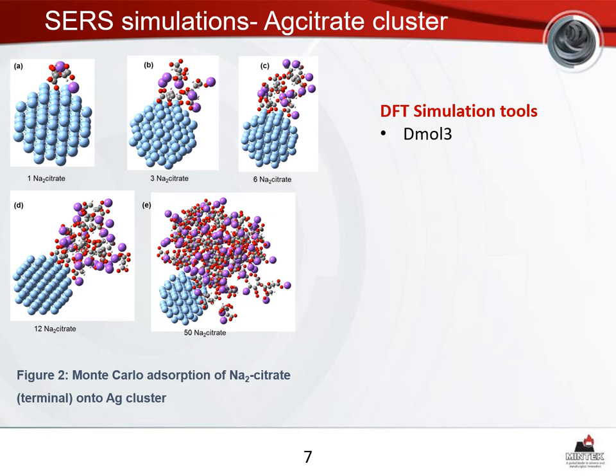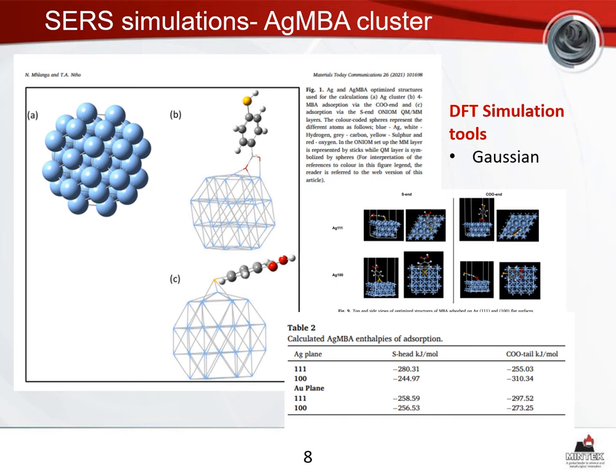This also controls the size, since everything is size dependent. Since we are sensing biological molecules, our system needs a Raman tag. We are using 4-mercaptobenzoic acid as our Raman tag, which has a thiol group on one side and a carboxyl group on the other. Using the HPC platform, we studied the chemistry of its binding to the nanoparticles — which facet it favors, which functional group favors which facet — and we deduced that there are even differences between silver and gold nanoparticles in terms of favored facets and binding terminals.